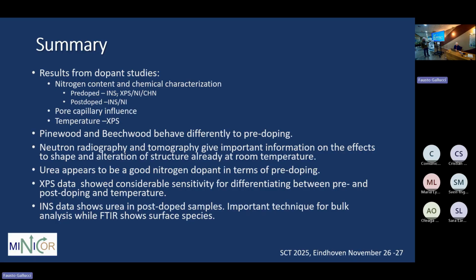And INS data shows to be useful in post-doped samples, an important technique to look inside the bulk of the entire sample, whereas FTIR is more surface sensitive. It is very hard with FTIR, when the sample gets highly carbonized, to see any spectroscopic features because it gets too attenuated, but not with neutron scattering.